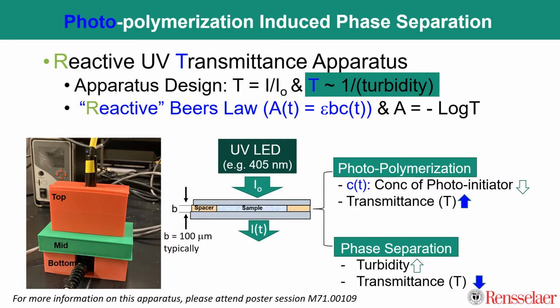This essentially will allow us to irradiate our sample with UV light, which will start our photopolymerization. As the photopolymerization continues, the concentration of our photoinitiator will decrease and our transmittance will go up. Another thing to note is that if our sample has phase separation, turbidity will go up and transmittance will decrease.